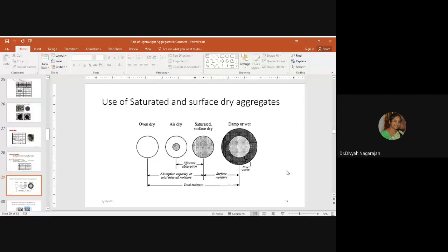So when saturated and surface dry aggregates are used, the additional water which we add during design is also accounted for. When oven dry aggregates are used, there will be no additional water available during concreting. But when air dry aggregates are used, a little amount of water will be available, and saturated and surface dry aggregates will be fully filled with water, and they will enhance internal curing of the concrete. Damp or wet aggregates, when they are used in concrete, will increase the water cement ratio or water content of the concrete.